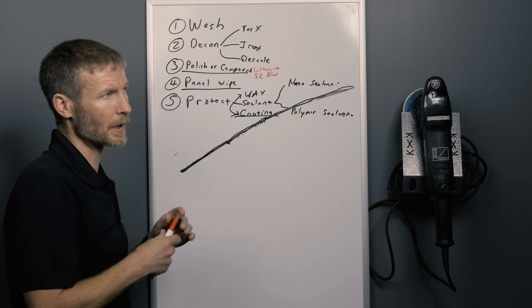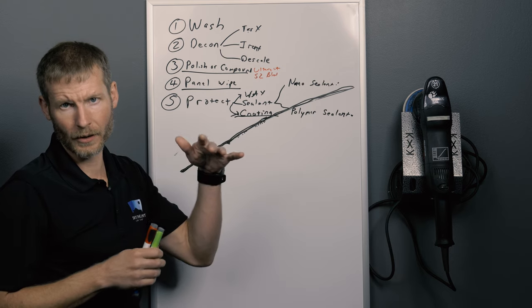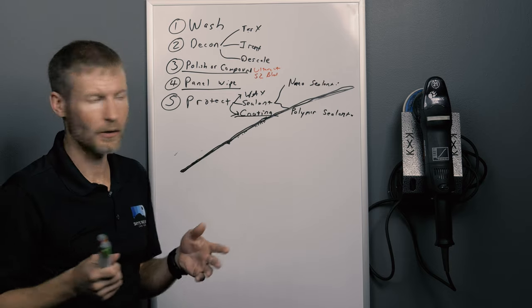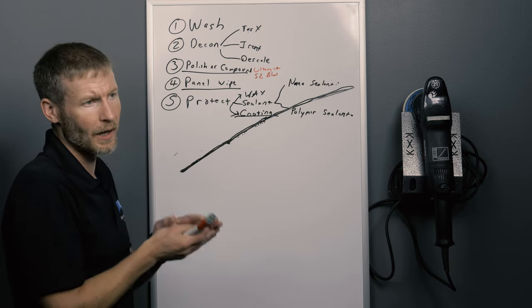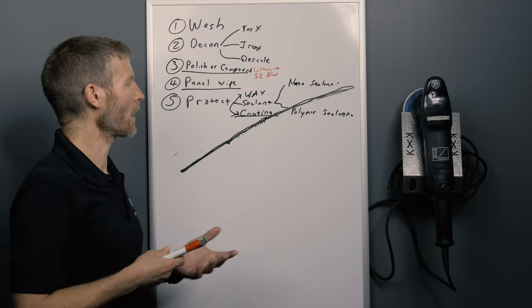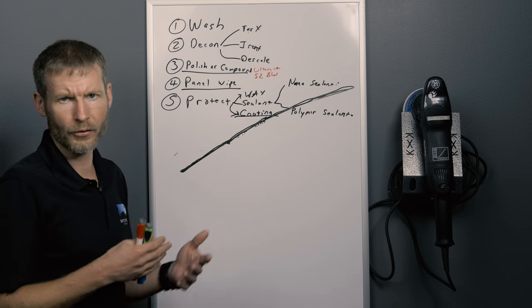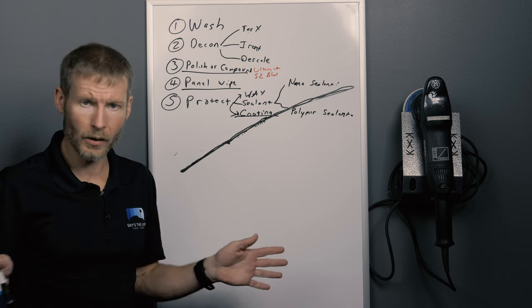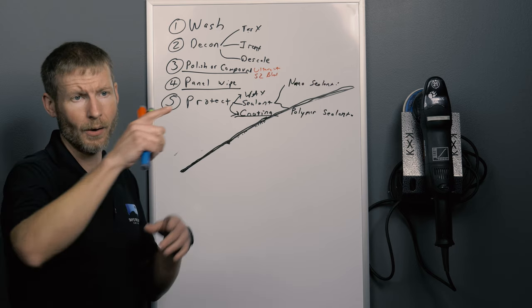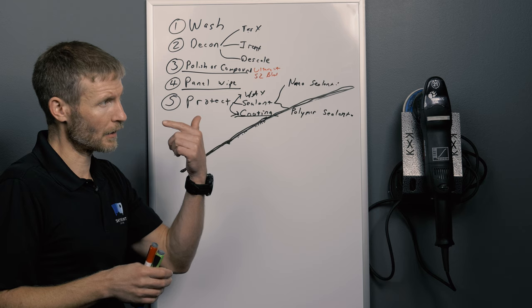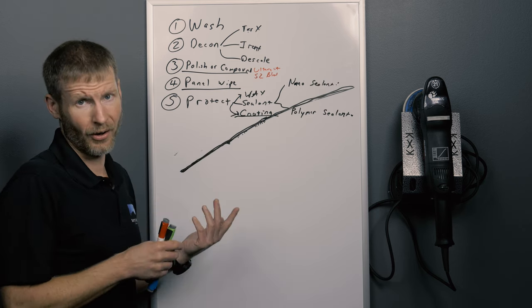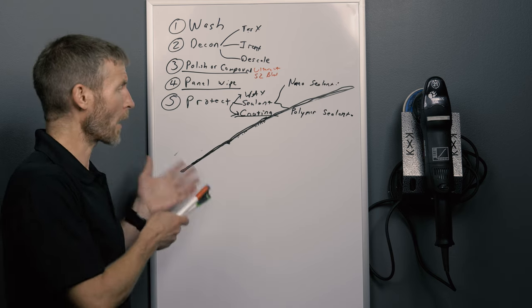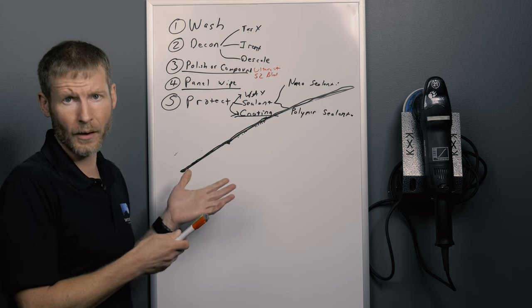We applied it as a liquid. By now it's a gel. I like to imagine, I don't know if it's accurate, but I like to imagine like a bowl of jello. And that jello is eventually going to become a solid. So during that time that it's a gel, you could eventually say four hours later, you could pour water on this and it's not going to wash off. Even four hours in, it's good. In a perfect world, you're not going to pour water across it. But just to give you a little bit of knowledge about how it works, at that point, the water is not going to wash it off. However, it is very, when it's in that gel state, it is very susceptible to water spots. So if you were to, for instance, say, oh, I got my car coated, it's fine. It's okay if I get water on it. I think I'll go for a drive. And you went to go for a drive and the guy in front of you on the highway sprayed his windshield wiper fluid and it had bad minerals in it and that landed on your paint and went down your paint, then you're probably going to get water spots there and they're probably going to etch it because it's a bowl of jello.